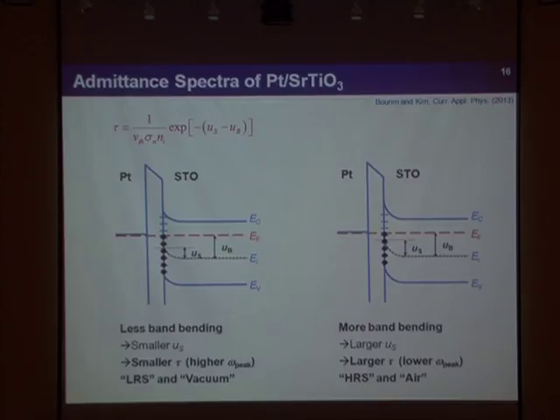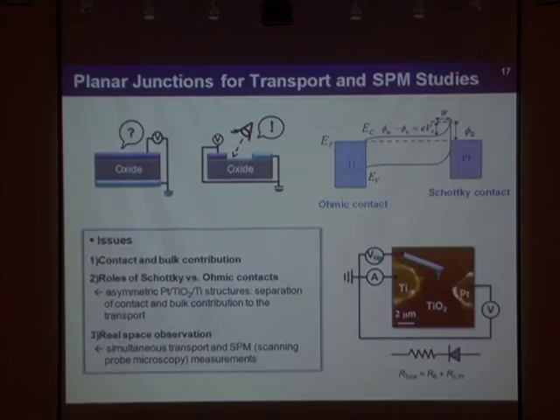The LRS and HRS state difference is also similarly found in the vacuum and air data. This means the trap states are strongly affected by the ambient condition. I'll talk about this ambient effect again later. From this result, we can say trap states are really important in the resistance switching behavior of our Schottky junctions. We believe the trap picture is more important, at least in our device.